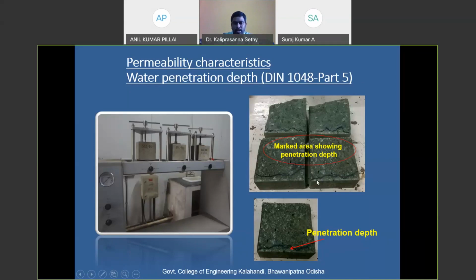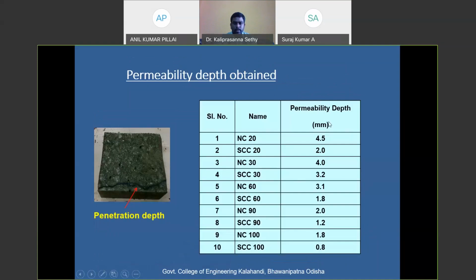You can see, immediately after breaking the sample, we mark the samples using this highlighter, because the permeability front may vanish due to evaporation. By using a scale, we took the readings of these concretes. And here is the permeability depth which we observed from the test, by taking the average from all the concretes. The maximum we observed is 4.5 mm. So you can see 4.5 mm is a very negligible depth if you consider the cover of the concrete, which is around 25 mm to 50 mm. So it is categorized as good resistance to permeability.